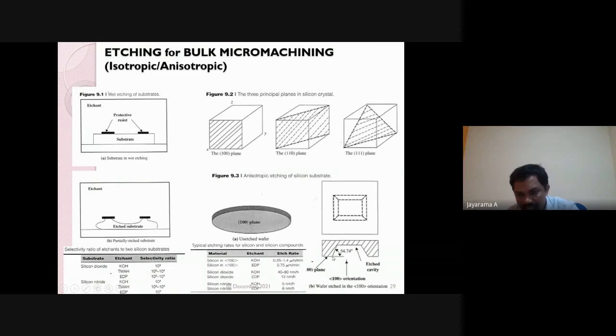Main information is about 100 orientation. Here in 100 orientation, wafer etched in 100, this angle is 54.74 degrees. You must know the planes of silicon wafers before etching, and the selection of etchant is very important to optimize the etch rate.